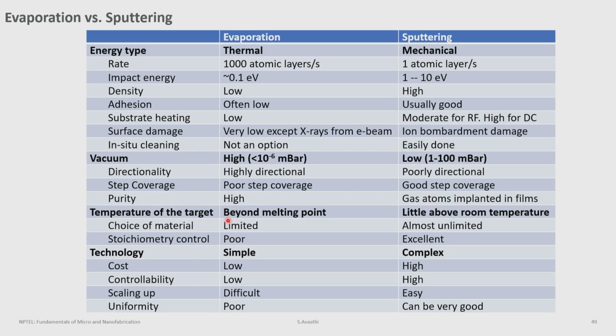The temperature of the target, this is the material that you are transporting. So this is melted, right? So you have melted, which means that you have limited choice of materials. Materials that are very hard to melt cannot be deposited. The stoichiometric control is poor. However, in sputtering, the target becomes a little hot, but because of water cooling, stays more or less at room temperature. And that allows you almost infinite choice of material. You can sputter tungsten, you can sputter refractory materials, you can sputter carbides, you can sputter nitrides, materials that have very high melting point. You can't evaporate those materials.